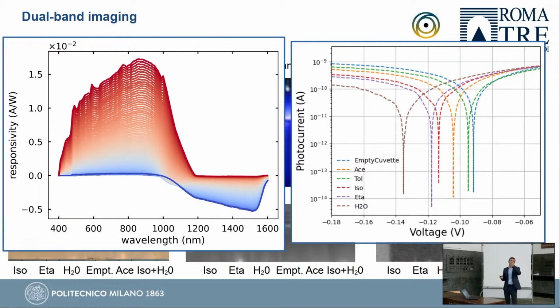You can go even farther, because we can continuously change the bias. So we can go from positive to negative in as many steps as we want. This is done every 5 millivolt. And so you have a continuous variation of responsivity, of photocurrent. What you can do is actually use this and scan not the wavelength, but the bias. And you obtain these different curves for the different bottles that we have seen. You see that we have some spectral information inside. Each bottle has a distinctive curve, especially this minimum here is different for every substance we are analyzing. So again, we can think about training some classifier to understand what we have in the bottle.